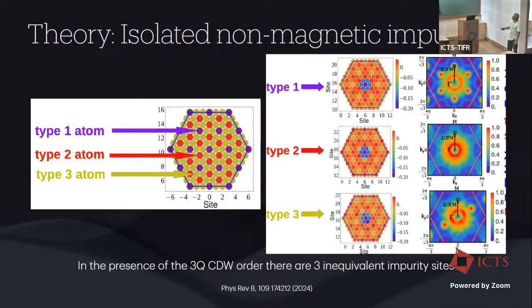Interestingly, if you now ask what happens in the presence of non-magnetic impurities, since you have a 3Q CDW state, and if you look at your lattice, there are actually 3 inequivalent impurity sites that get generated. And if you were to try to calculate, let's say, self-consistently what happens to the CDW order parameter or the electron densities near these, you find that locally, 2 of these sites out here lead to a local structure which has a 6-fold symmetry in it, but from this particular point itself, if you have a non-magnetic impurity, you get these clear-cut 2-fold symmetry forming in the local Fourier transform.